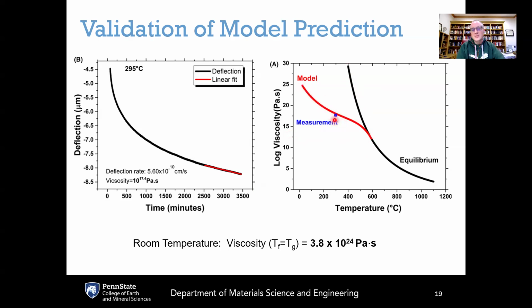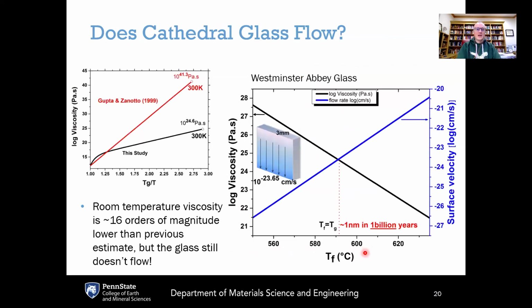The lowest temperature viscosity measurement taken by Oscar is this blue point shown here, and you can see very good agreement between the experimental measurement and the model prediction. And based on this, and then extrapolating this curve down to room temperature, the room temperature viscosity of Westminster Abbey glass was then found to be 3.8 times 10 to the 24 Pascal seconds. If we just put all that in the exponent, 10 to the 24.6 Pascal seconds.